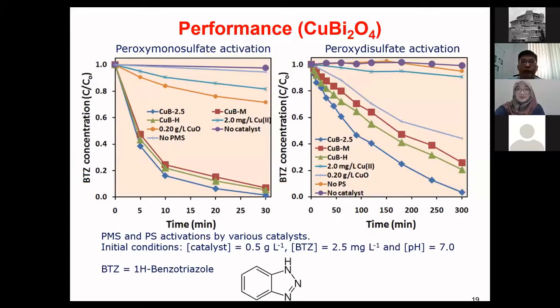The copper ferrite has a significantly higher leaching because it was prepared at a low temperature. So if you look at materials, if you prepare at lower temperature, the crystallinity of the materials will be lower. Most of the time it's lower. That's why you can see quite a large amount of leaching problem. So for this one, copper bismuth oxide, we have about 0.2 to 0.3 milligram per liter of copper leaching, and we are also not very satisfied with this. So this is something that we need to improve.